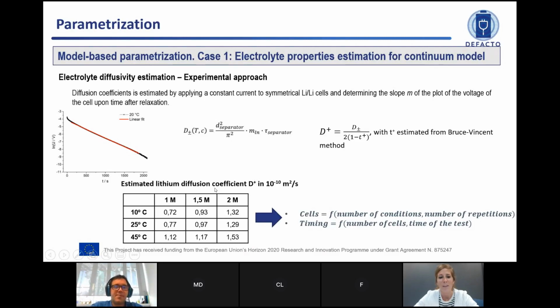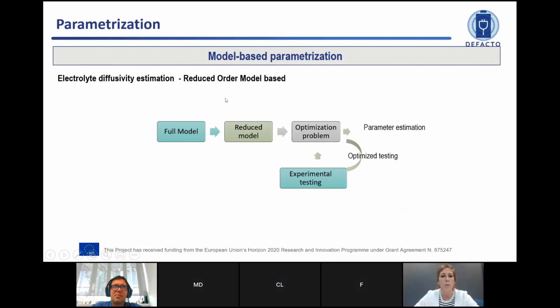So if we want to increase the number of values depending on these variables, the number of cells to be assembled would be huge, and it's quite time consuming. So what we are proposing here is to rely on reduced order models, because in the end we need to solve an optimization problem. The optimization problem basically wants to minimize the error between the simulated voltage and the experimental voltage, and this is quite time consuming. So we need efficient codes or efficient models that mimic all the multiphysics, and then perform this algorithm optimization to later estimate the specific parameters.